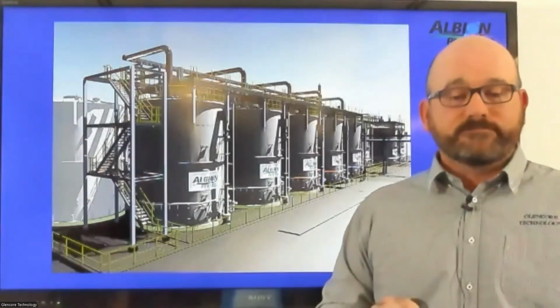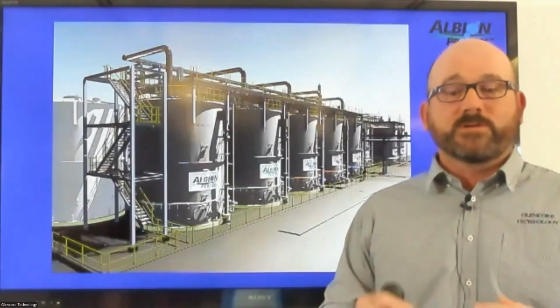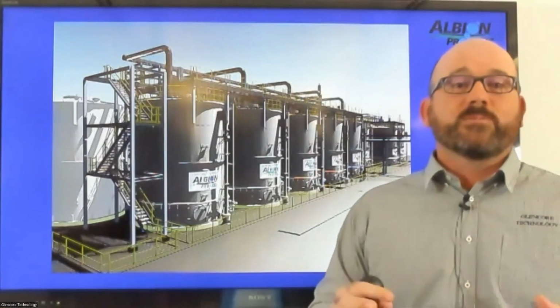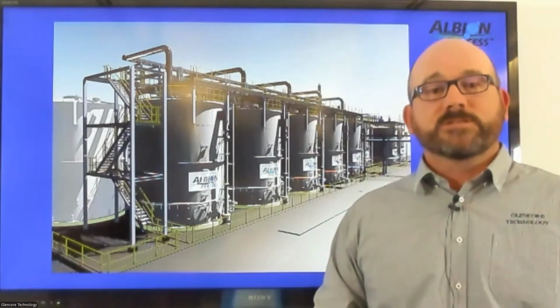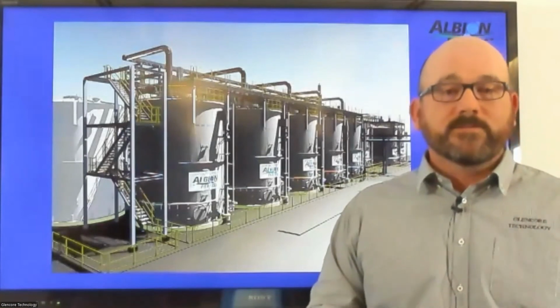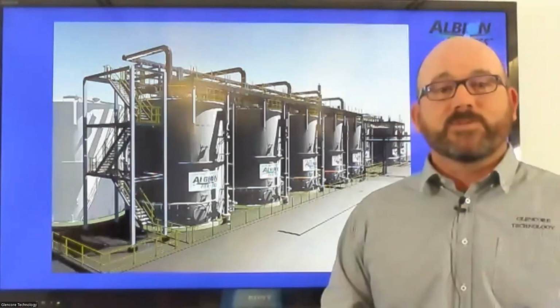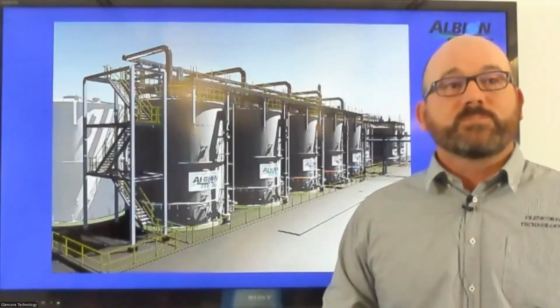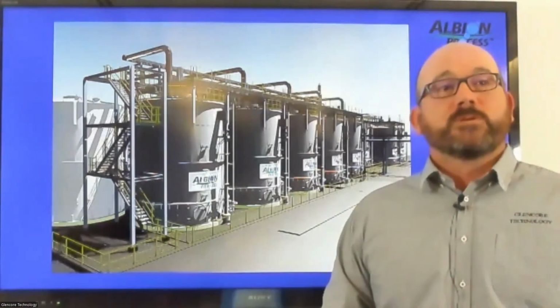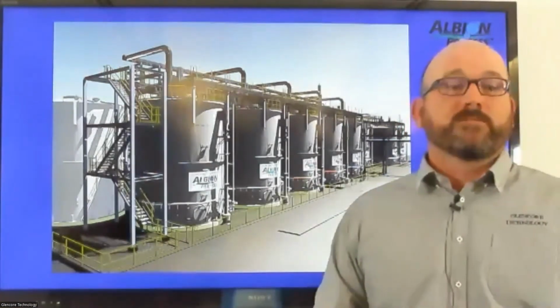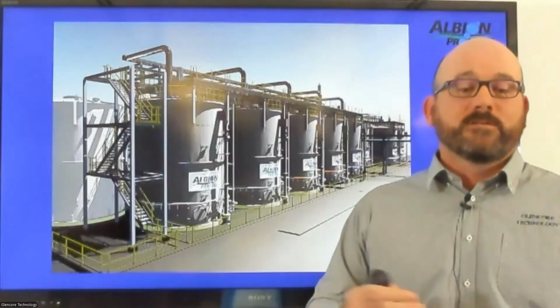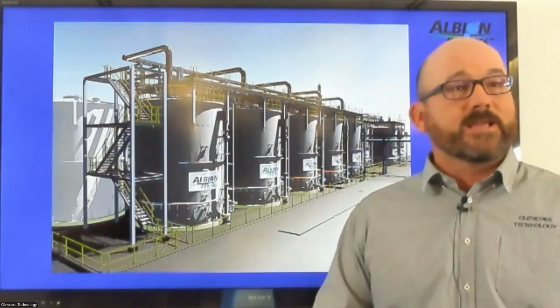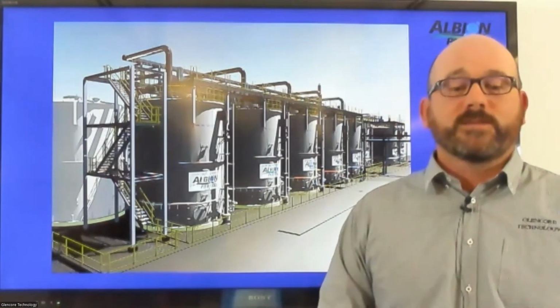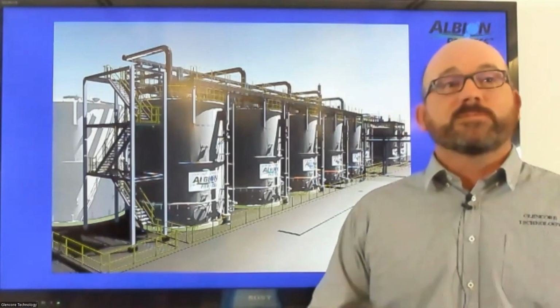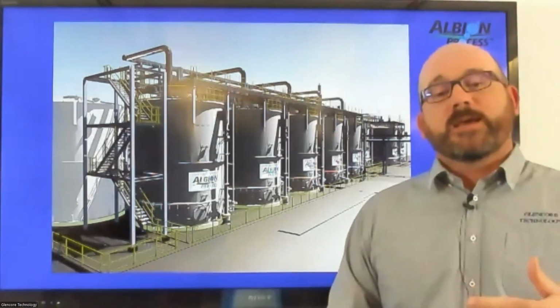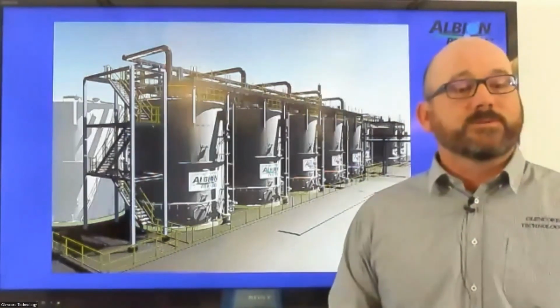The key part for our leach reactor design is that we've done the test work and the kinetic work, so we can work out the mineral rate constant. The leach reactor is designed such that the agitator input power ensures that oxygen diffusion is not limiting the leaching of the mineral, along with the power inserted through our oxygen sparge, the Hypersparge. So we can get that rate constant, which typically for pyrite and chalcopyrite is a first order rate constant. From that, we can put it into our models, using a CSTR to get a very accurate model of the leach reactors, and work out the residence times and the heat and mass balance to do the sizing, and to scale up from the bench scale test work for this design.